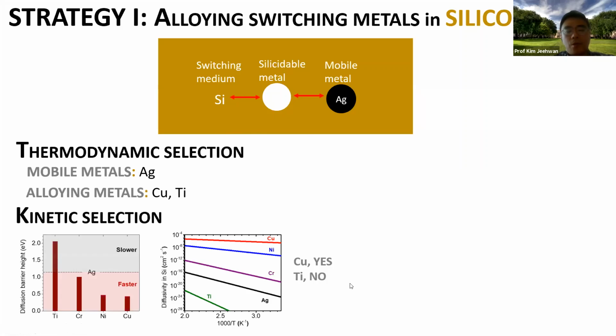However, we also need to consider the kinetics. As you can see here, the diffusion barrier of titanium is much higher than silver, meaning that even if you alloy the titanium with the silver, titanium is not moving faster than silver, so the alloying effect is not very high. So now we screen out the Ti, so copper is the perfect candidate. By just following this material logic, we were able to successfully find an excellent alloying element to have excellent neuromorphic computing. Please see below.